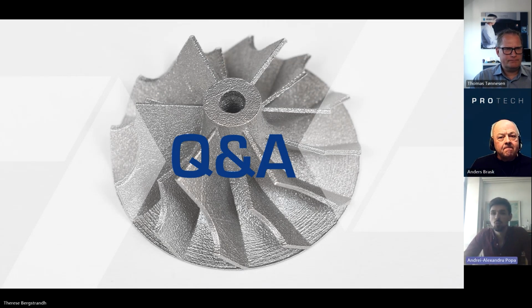Yeah, one obvious difference is that the soft recoater needs replacing more often than the hard recoater. However, it's a very cheap consumable. It also means that if you are in doubt that the recoating is done well, you have a go-to place to approach the problem from. You just open the thing and it's very fast to do. Quality-wise, if you forget to replace the recoater and it starts getting damaged, because it's soft and in a 100-degree environment, then you risk having bad recoating. So that's something to consider for sure.